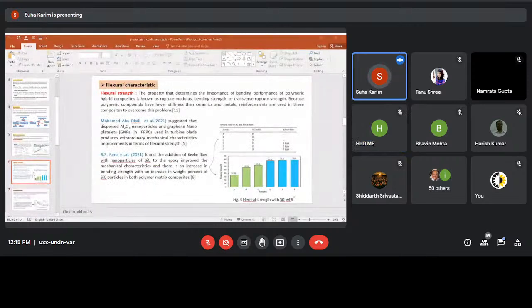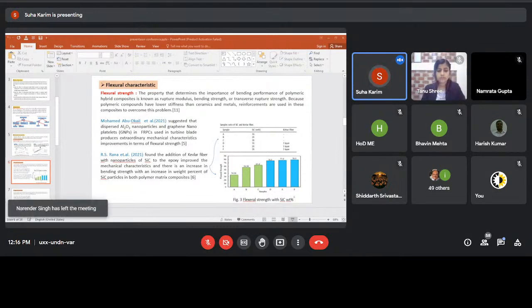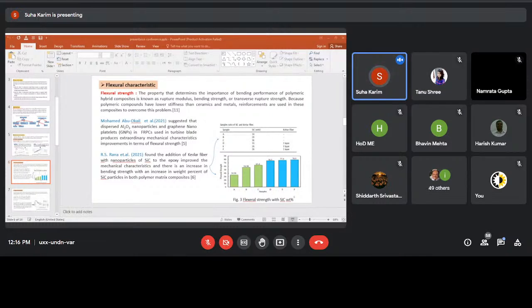Related to another property, which is flexural strength, which is also important for the bending performance of polymer hybrid composites, and it is known as rupture modulus, bending strength, or transverse rupture strength. Polymer composites have lower stiffness than ceramics and metals. Reinforcements are used in these composites to overcome this problem and increase the lower stiffness. Mohammed in 2021 suggested that adding alumina nanoparticles and graphene nanoplatelets in fiber reinforced polymer composite used in turbine blade produced an increase in the mechanical characteristics, especially the flexural strength.